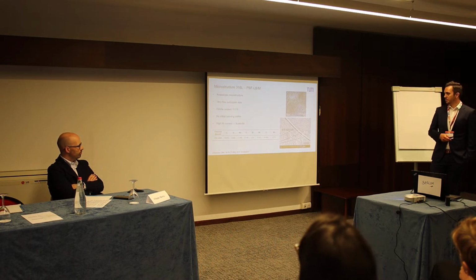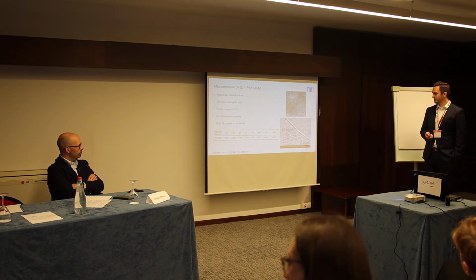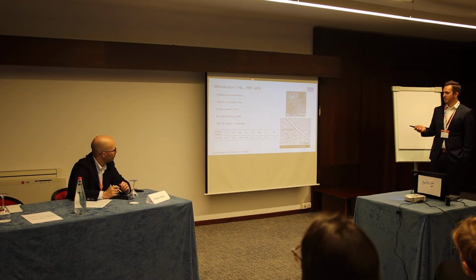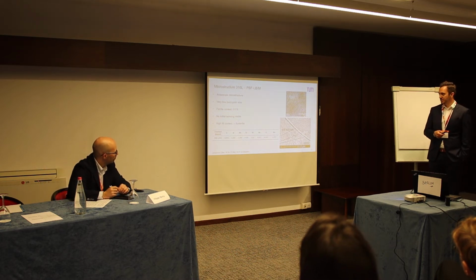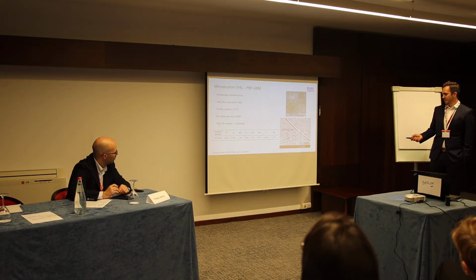So let's get to the microstructure before loading. And as we can see, for the PBF-LB manufactured 316L, we have, as expected, an anisotropic microstructure with very fine subgrain size, varying between 400 to 600 nanometers.